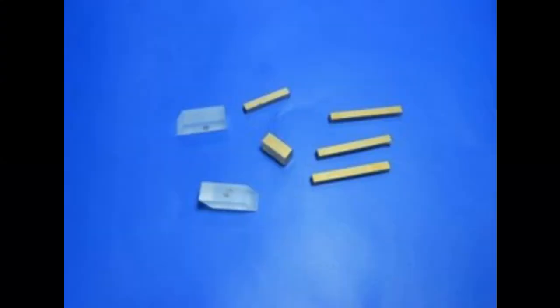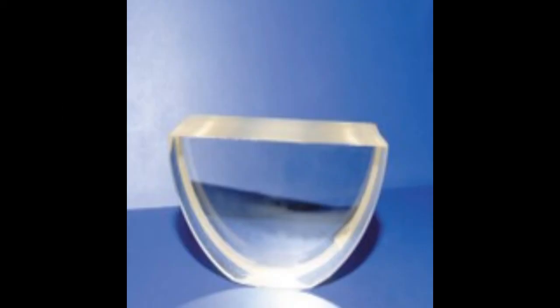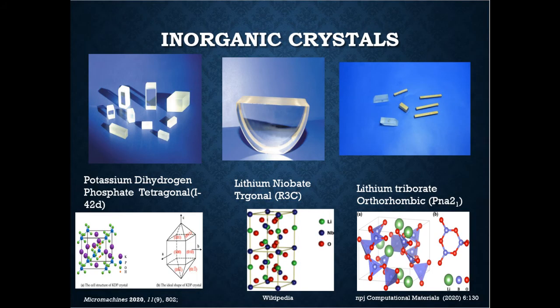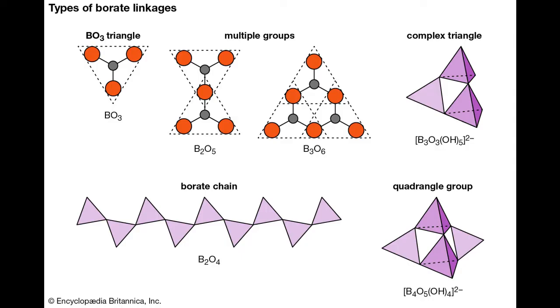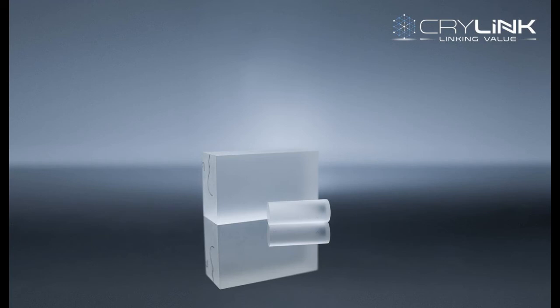Historically, quartz crystal was the first material used in the demonstration of the second harmonic generation of light with ruby lasers. Subsequently, many systems like perovskites, tungsten bronze type materials, iodates, phosphates, nitrates have also shown non-linear effects. In all of these materials, the anion group has been identified to produce high non-linear microscopic effects. It has been established through detailed studies that, in general, borate compounds have better advantages of being non-linear materials in the UV range. They possess transparency in the UV and deep UV regions. Due to their wide band gap, they also have high damage thresholds.